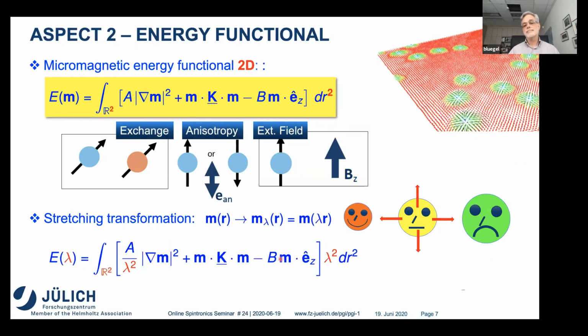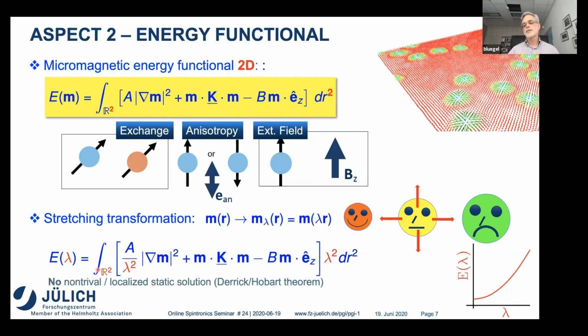Then you see, due to this r² term here, you get here a lambda square term. And since you have here a first derivative square, you get here a 1 over lambda square term. And if you plot this function now as function of lambda, then you see the minimum of this function is at lambda equals 0. That means if you put your skyrmion onto this ferromagnetic state, described by this energy functional, the skyrmion will be squeezed to 0, will be squeezed to death, and your skyrmion might be a delta function or a singularity, or might not exist.